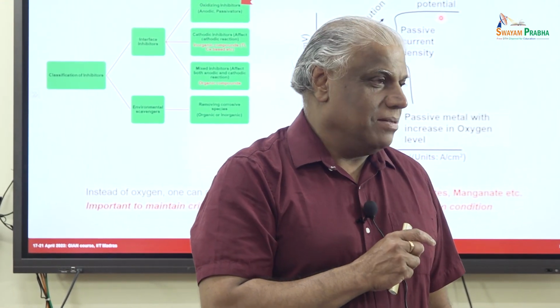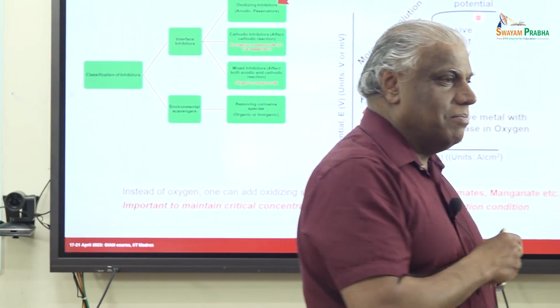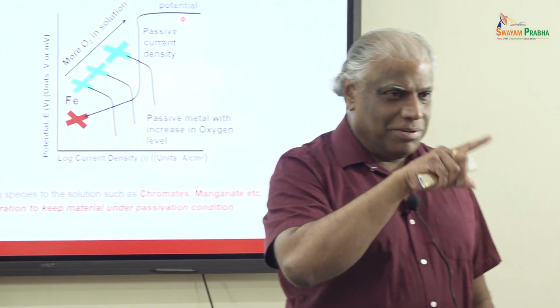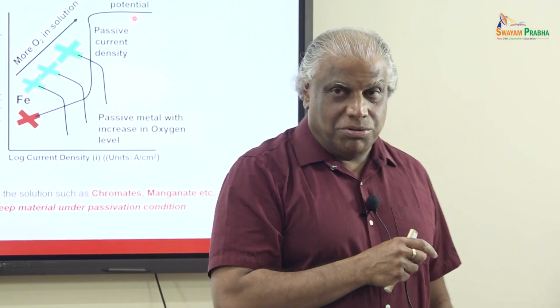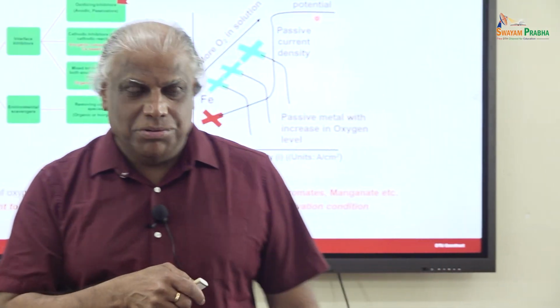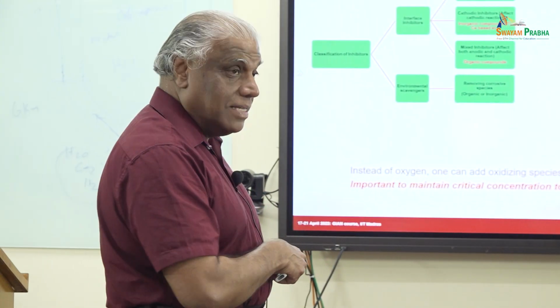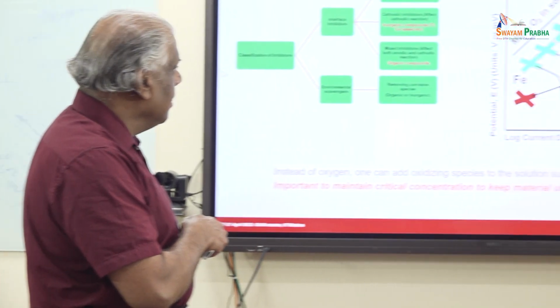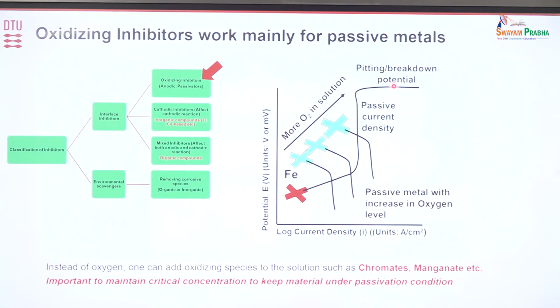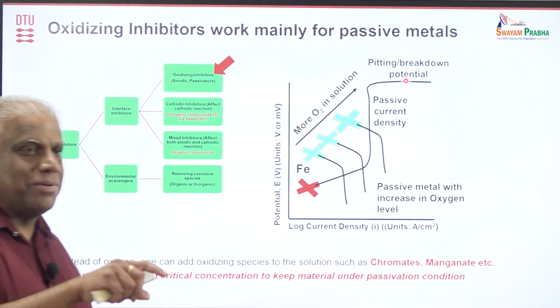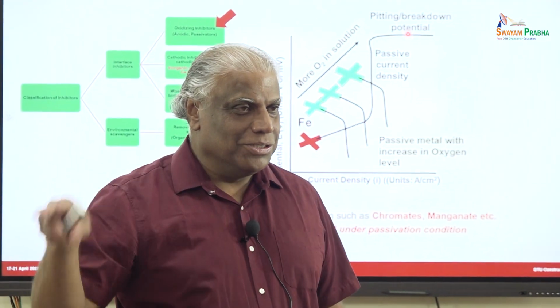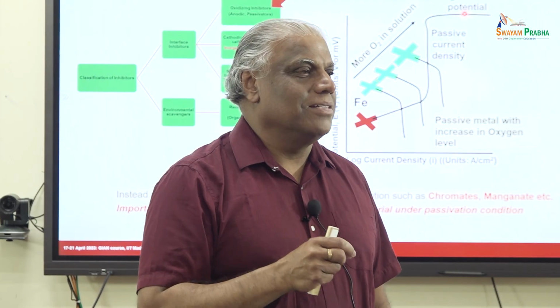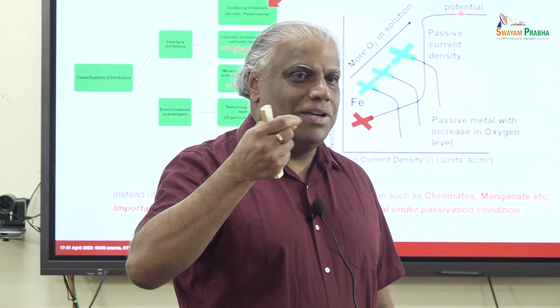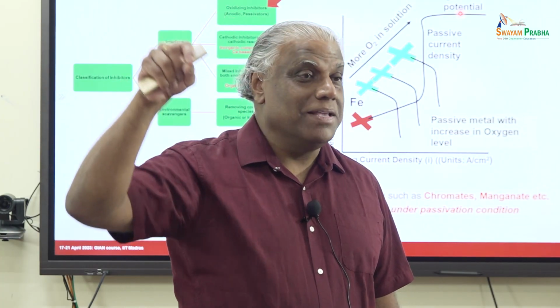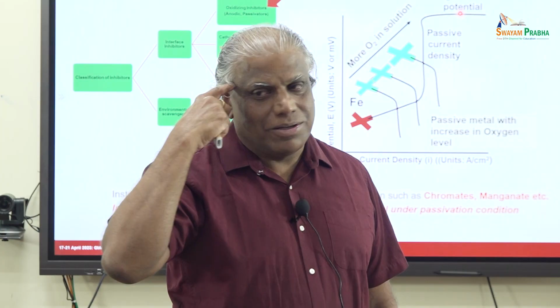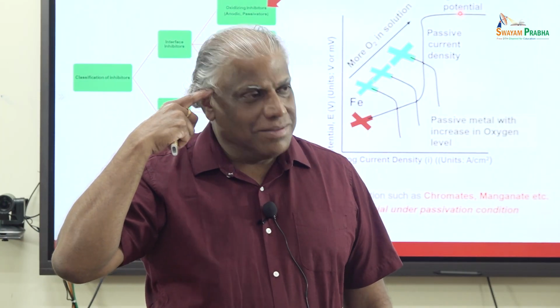Because of the design of the component. For example, in heat exchangers, you have many bends and things like that. So somewhere, if the solution is stagnant, the stagnancy makes the concentration of the chromate higher in that region, and then you raise the potential into the pitting potential value, and you get the corrosion problem there. You expected that you kept the concentration constant and would not have any problem, but because of the kinks and things like that, you raise the concentration in that region, and suddenly you will see pitting. So when you do the failure analysis, you will see the pitting in some places, and you don't understand because you think the concentration used is enough, but this is the reason that it is happening.